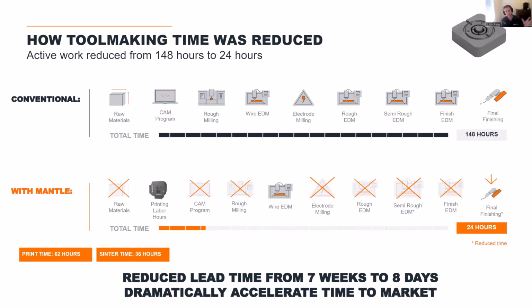How do they actually remove all this tool making time and all this tool making cost? By removing a lot of the active work involved. As you can see on that top, if you're familiar with tool making, a lot of different steps are involved in building this part, from the actual CAM work, the rough milling, the wire EDM, the electrode milling design and production, which is always a very, very time consuming step. And then of course, all the EDM work that would have been involved to sinker out these deep features. They estimated that was going to take 148 hours of their toolmaker time. With Mantle, they simply printed it, did their wire EDM, did a little bit of final finishing, and down to just 24 hours.